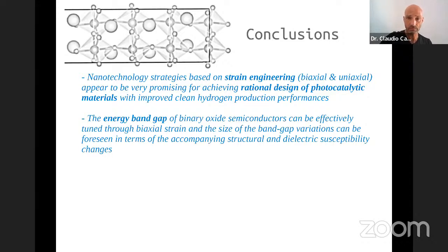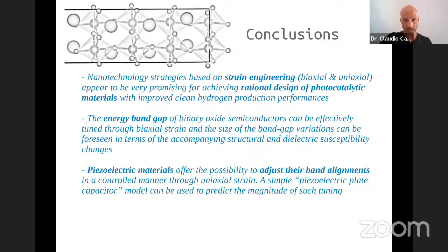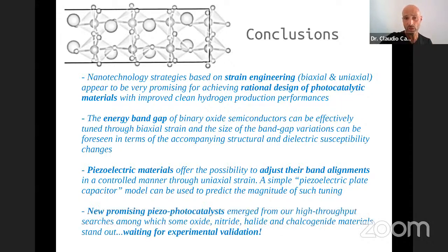The energy band gap of some of those materials can be understood in terms of well-known symmetry breaking arguments. And out of our work on piezoelectric materials, we have shown that piezoelectric materials can really offer a rational way to adjust band alignments in a controlled manner. This is something that you may not find in other families of materials, so it is a very important conclusion of our work. We have shown that many overlooked piezophotocatalytic materials could be checked in practice and validated in experiments, since according to our calculations they are very propitious in terms of band alignment tunability.